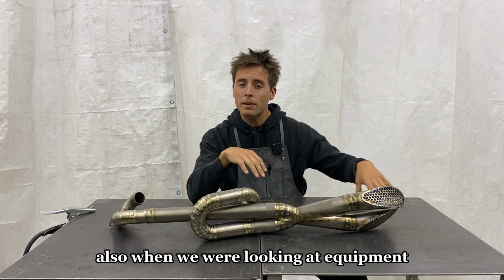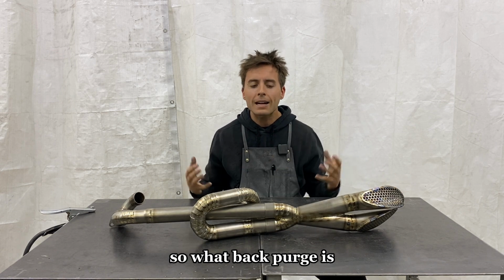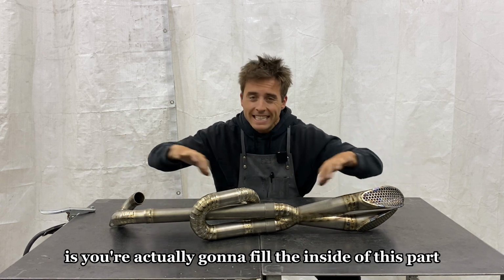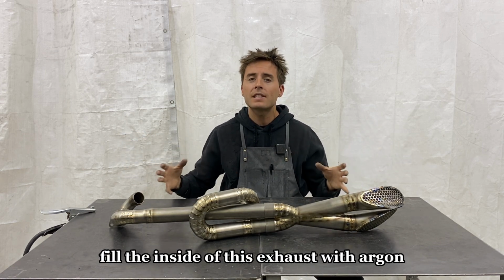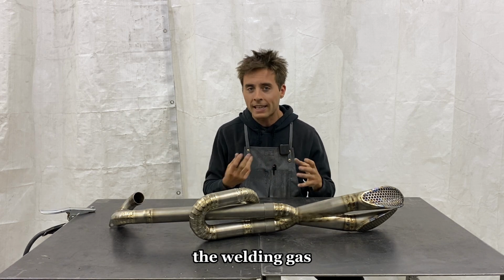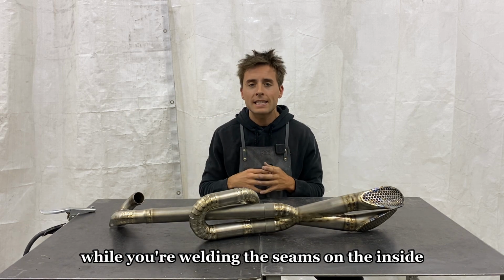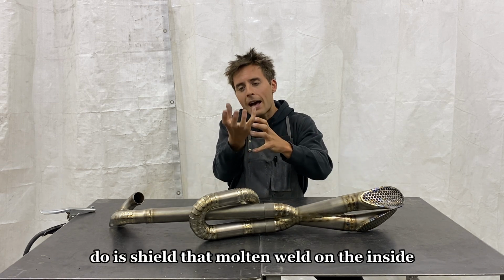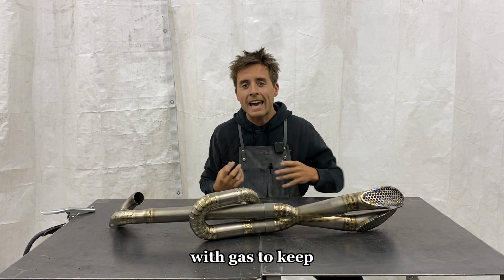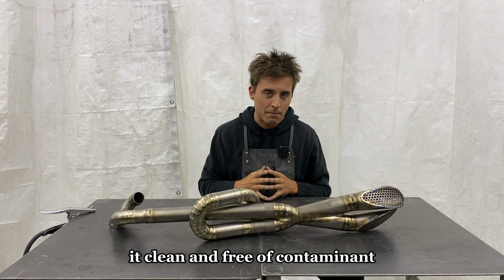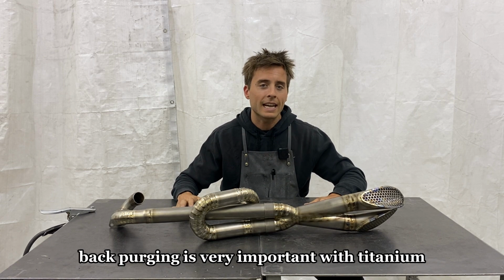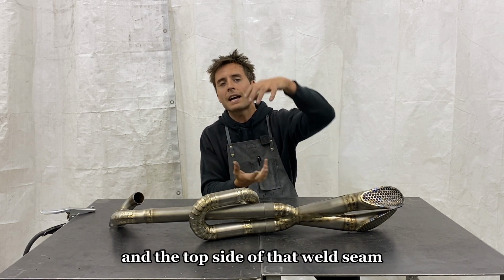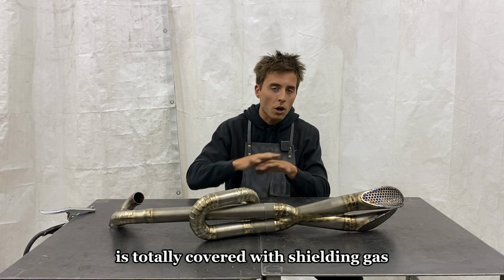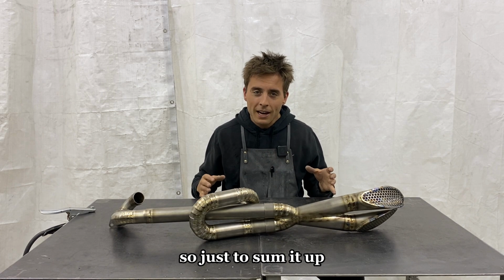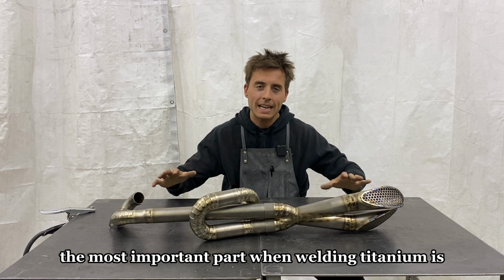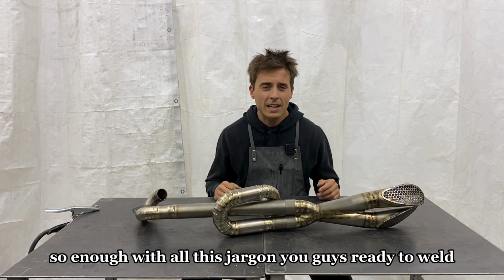Also, when we were looking at equipment, we were talking about back purge. What back purge is, you're actually going to fill the inside of this part, fill the inside of this exhaust with argon, the welding gas, while you're welding the seams on the inside. What that's going to do is shield that molten weld on the inside with gas to keep it clean and free of contaminants. Back purging is very important with titanium. You want to make sure the bottom side and the top side of that weld seam is totally covered with shielding gas. So just to sum it up, the most important part when welding titanium is your gas coverage.